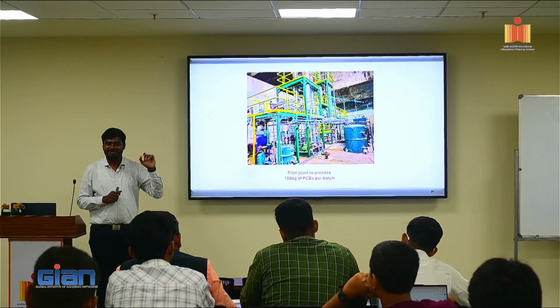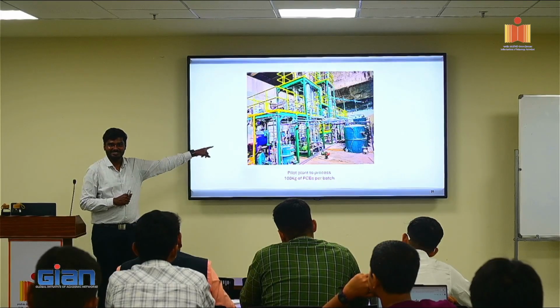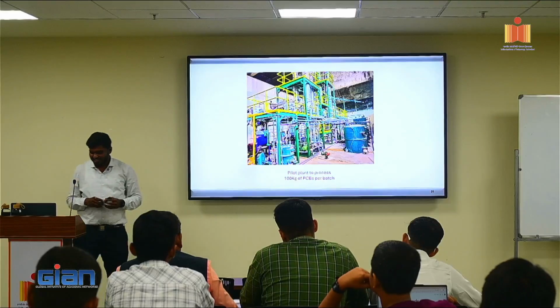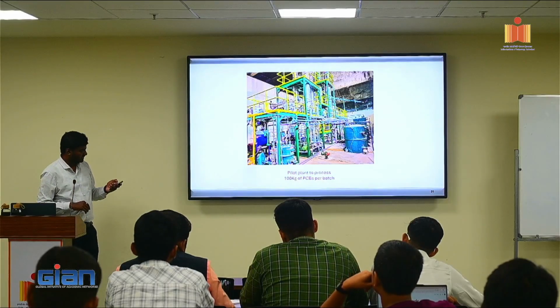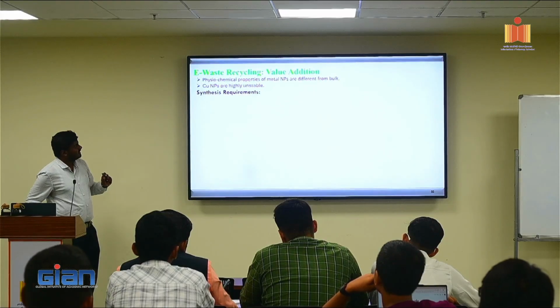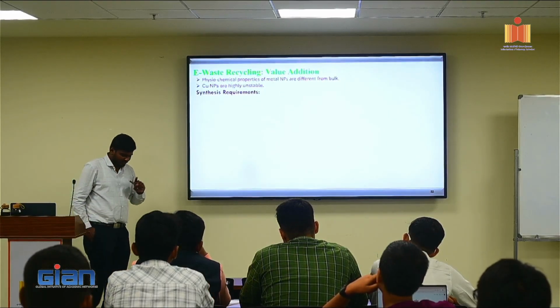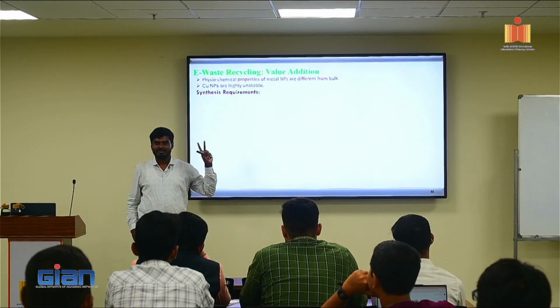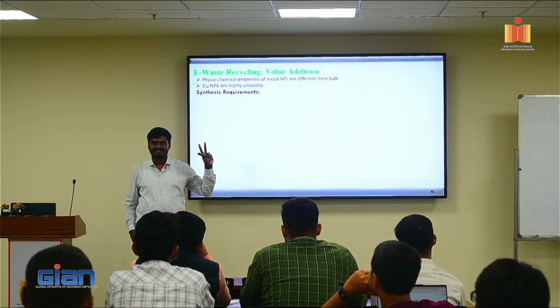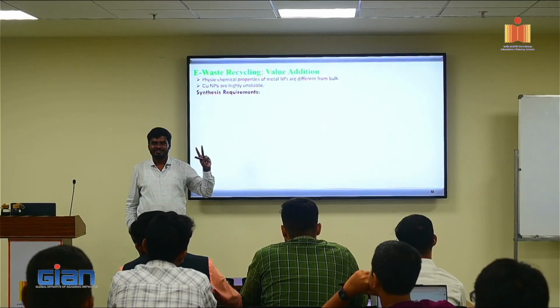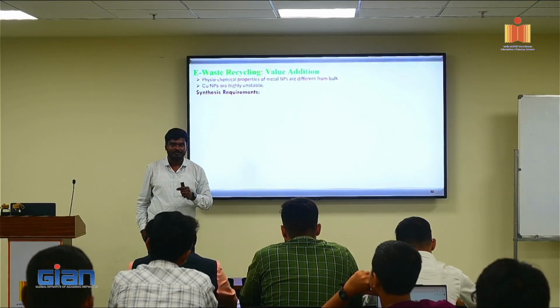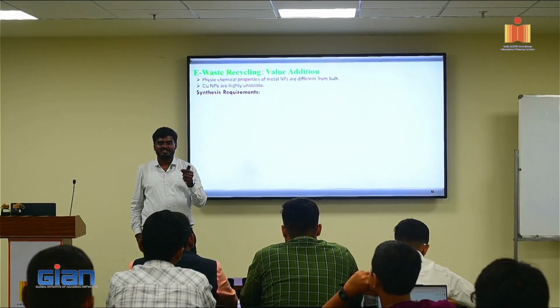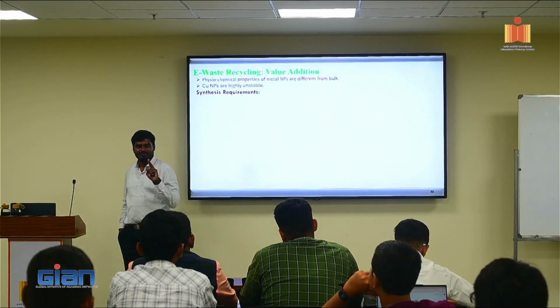That was another problem that I worked on in my PhD, parallel to the scale-up research. So I'll just give a brief overview about those copper nanoparticles and then I'll stop. The challenge is that whenever you go for metal nanoparticles, people work on gold and silver. The reason is that they are highly stable. Whereas when you go with copper, it gets oxidized very quickly. The moment you synthesize it, within a fraction of a second or milliseconds, it gets oxidized and you get copper oxide.